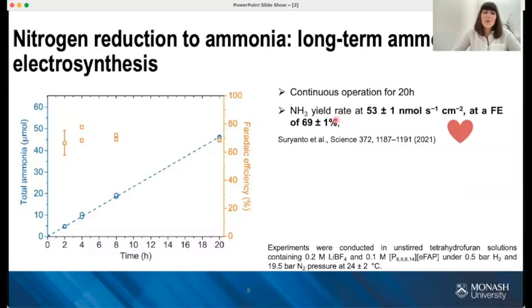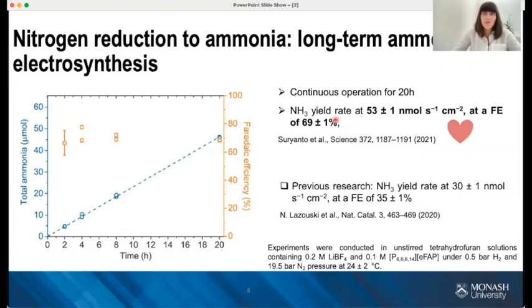It is a notable improvement upon the best reported system so far, which you can see here, where the authors of that paper produced ammonia at a yield rate of 30 nanomoles per second per centimeter square and a Faraday efficiency of 35%.